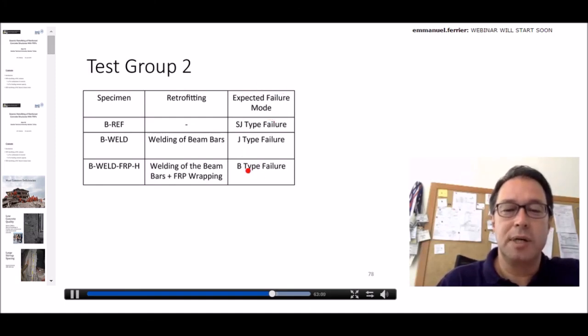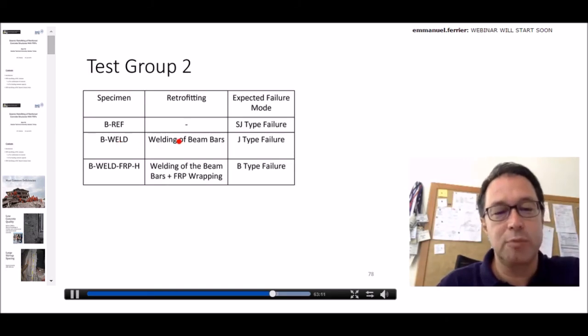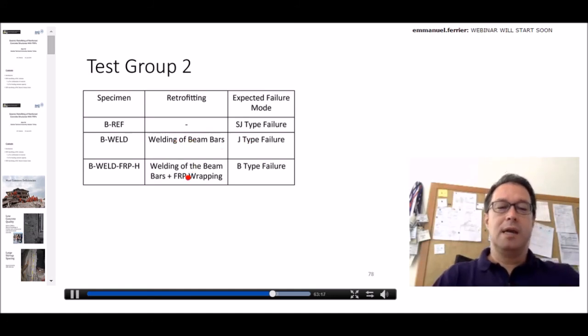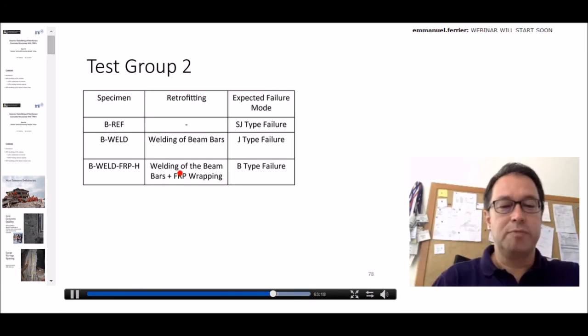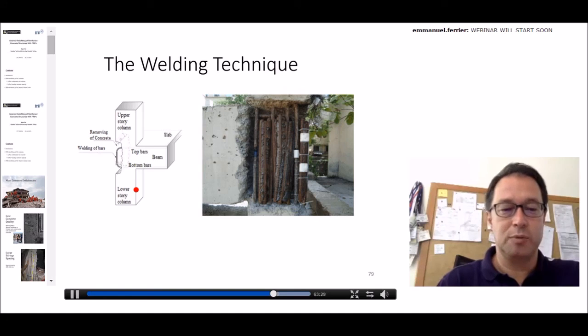Again, we had slip and then joint failure in the reference specimen. And when we avoid slip by welding of bars and also replacing the weak concrete around the hooks of longitudinal bars, then we had shear failure in the joint. And when we do both, which means we weld the beam bars and also use FRP sheets on the joint, we could reach beam flexural failure, which was what we targeted.